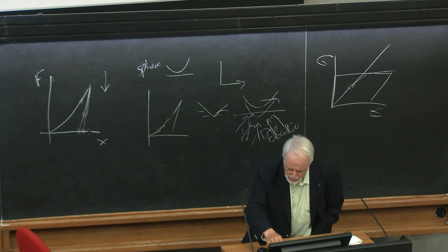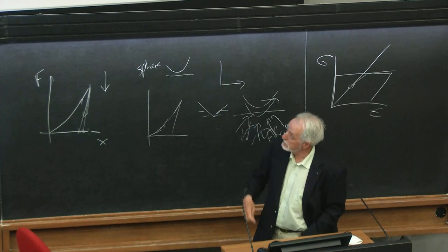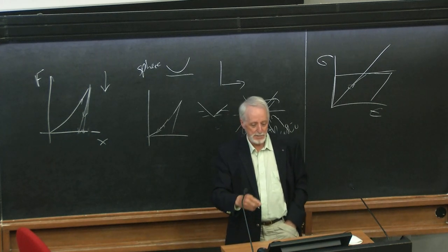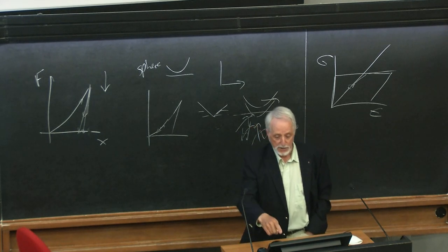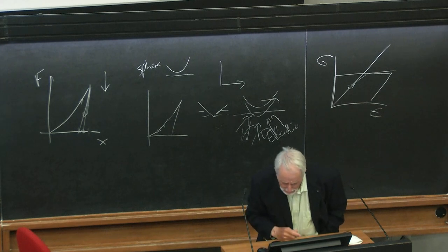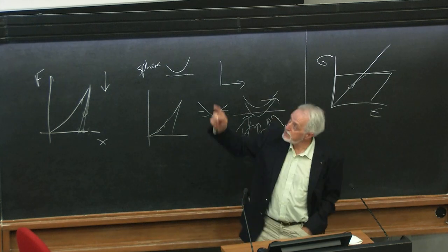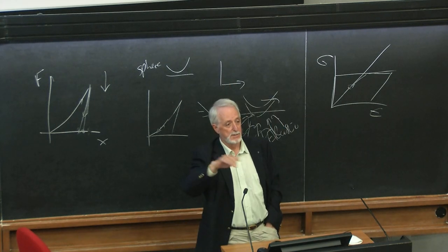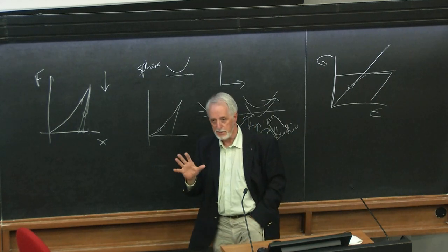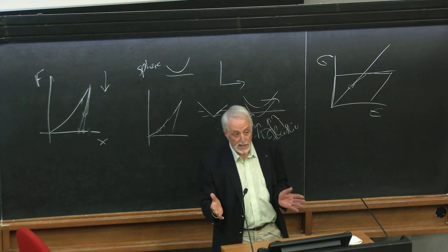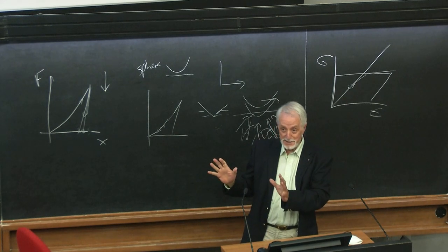And in fact, what you see here, as I say, depending on low E over H, that's to say high yield strain, what you find is the back follows the front, okay? And when you're then measuring the vertical contact area, you find you don't get the behavior you had before. What you find is it follows on there, whereas in the materials which are high E over H, that's low yield strain, you find, in fact, the back seems to break away, and this changes the way in which it moves into the surface and in which you get contact area, real contact area in the system. This is quite a complicated story, and I'm not going to say much more about it because there's large tracts that we still don't understand, okay, and there's some issues with it. Not in the experiments, by the way, it's more in our understanding.